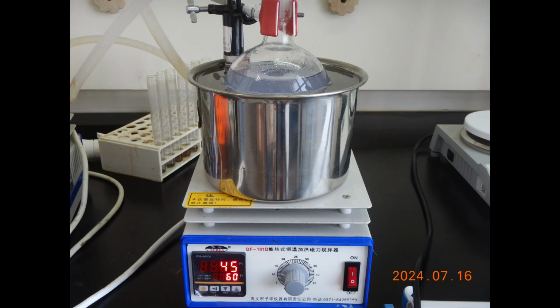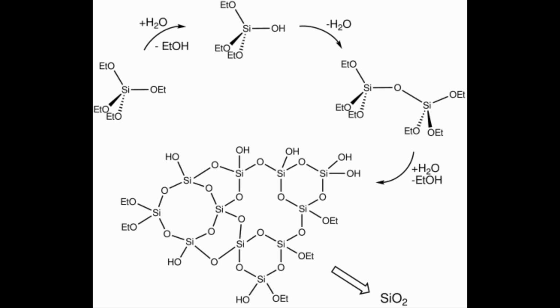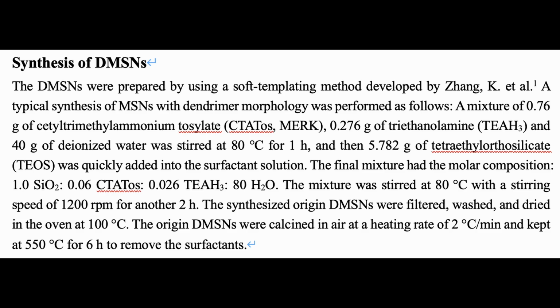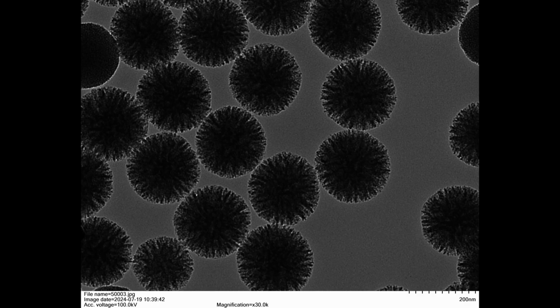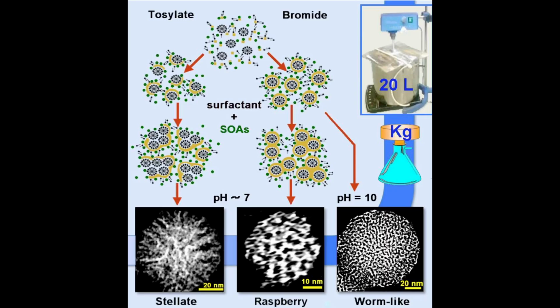The silica nanoparticles are prepared by the hydrolysis of tetraethyl orthosilicate in ethanol, which is the standard method, but a precisely controlled mix of cetyltrimethylammonium tosylate and triethanolamine surfactants must be added to form the unique and orderly spherical structure that we want. It's really interesting that even just changing the anion from tosylate to bromide can significantly alter the shape and morphology of the nanoparticle, so sticking to this recipe is key.